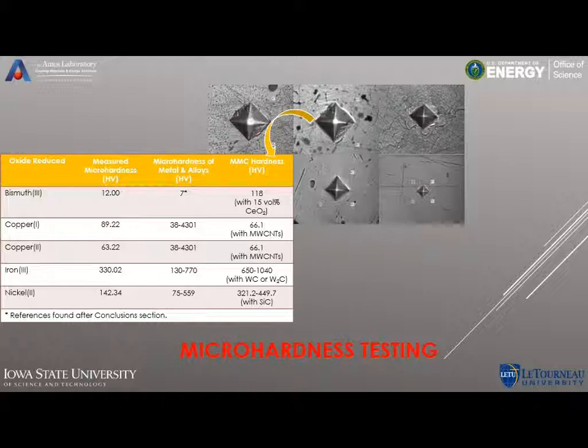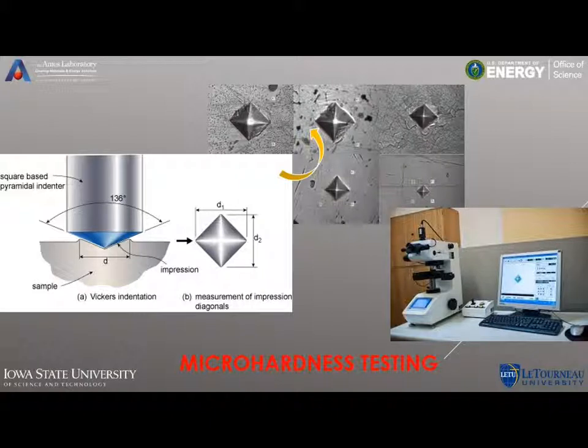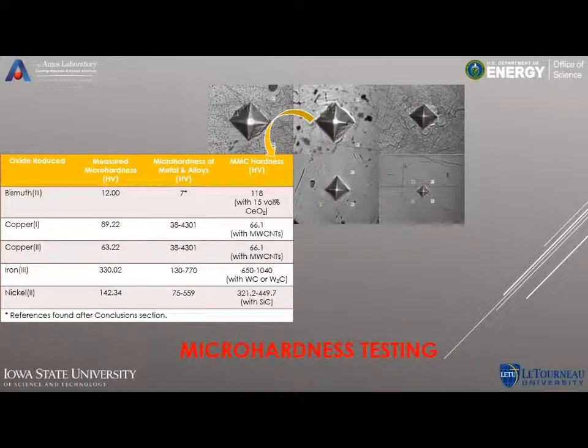Here are the actual measurements that I obtained. These were Vickers hardness testing. And so it's based on the pattern of the indent. It's the diamond pattern. So it's measured in HV, hardness Vickers. But the first column shows the measured hardnesses, and then you have the reference hardnesses in literature, and then hardnesses reported for different metal matrix composites.